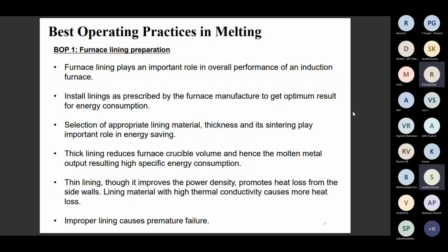So, best operating practices in melting. There are 10 best operating practices. First one is furnace lining preparation. Furnace lining plays an important role in the overall performance of an induction furnace. The lining should be installed as prescribed by the OEM furnace manufacturer to get optimum energy consumption. Selection of appropriate lining material with proper thickness, and the sintering, also play a major role in energy saving. A thick lining reduces furnace crucible volume and hence the molten metal output, resulting in high specific energy consumption.